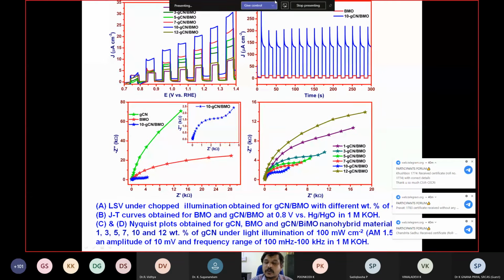Now you just look at this. I have designed the catalyst by considering a visible light active material. Then the band position is also suitable, so that also we have designed. Then the charge transfer resistance, that means the charge separation and migration process, that also we have fulfilled. Finally, I checked the stability, and it shows excellent results. So my material fulfills all the criteria for designing efficient photoelectrochemical hydrogen production.